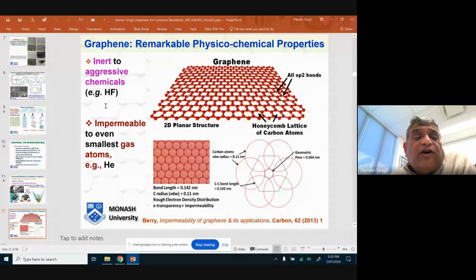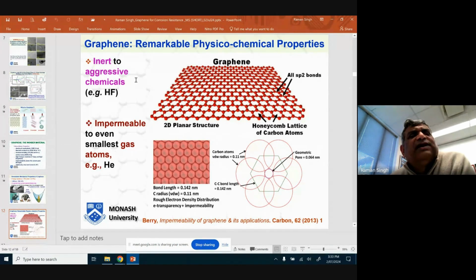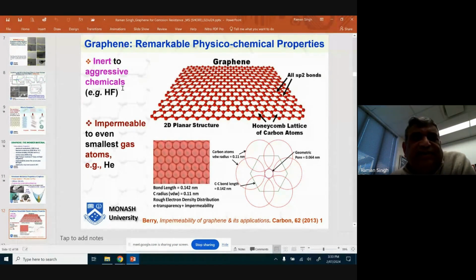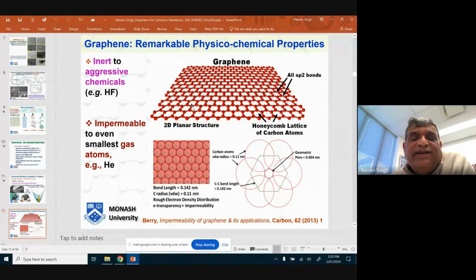tough. Graphene is also inert. Even the highly aggressive hydrogen fluoride does not attack graphene. So the species that cause corrosion, like mild acids or chloride or oxygen or water, they don't have any chance of reacting with graphene. So graphene is inert, whereas common coatings like polymeric coatings, they can be attacked. They can degrade because of ultraviolet rays or caustic or other chemicals. Graphene does not undergo any chemically assisted degradation at all.